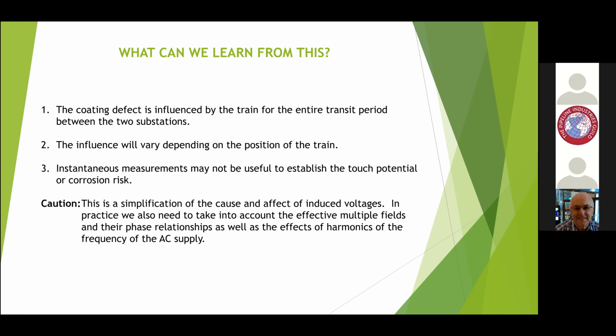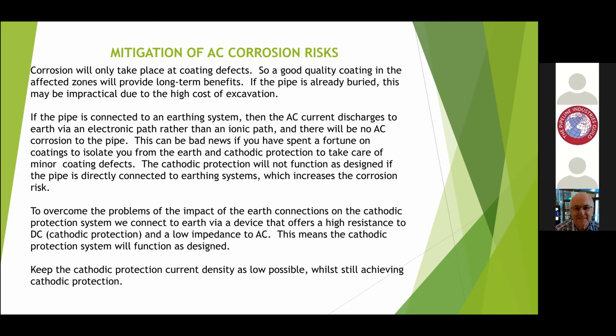So what's important to take away from those little sketches there is that the poor old coating defect is suffering all the time. And if the current density on the defect approaches a certain level, then we need to do certain things. And if there's cathodic protection on it as well, we need to do certain things. So the question is what we're going to do about the AC corrosion risks.